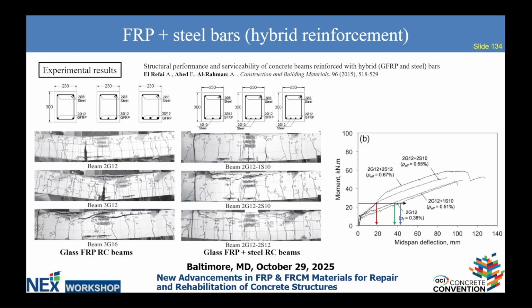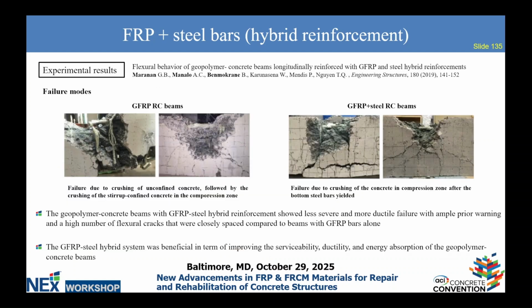And so you can see here that obviously if you increase the effective reinforcement ratio, which combines the two materials, using the GFRP, you will obviously increase the strength and the moment capacity, and in terms of deflection, there is not a big difference. And this is again because in this particular case, the reinforcement has not been placed on the same layer.